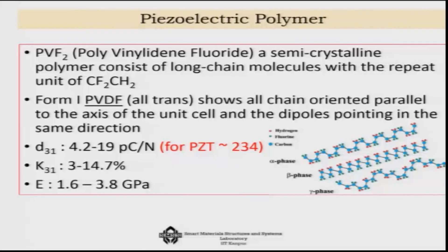Piezoelectricity is also observed in polymers, not only ABO3 ceramics. It was discovered in Japan that PVDF (polyvinylidene fluoride) in its all-trans state, where all dipoles are in one direction, shows a good amount of piezoelectricity in the polymeric chain. Although it is only about 19 picocoulombs per Newton compared to PZT's 234 picocoulombs per Newton, the advantage is that these polymer materials are more flexible. Unlike ceramics, you can give them arbitrary shapes, making them very useful for application as a layer on curved surfaces.